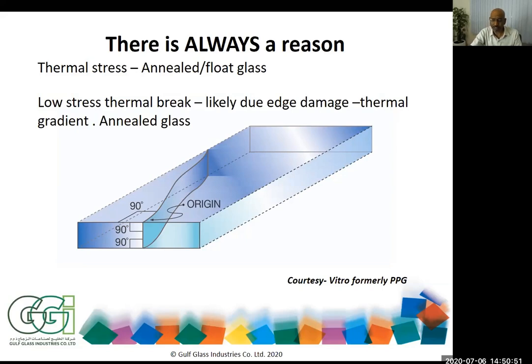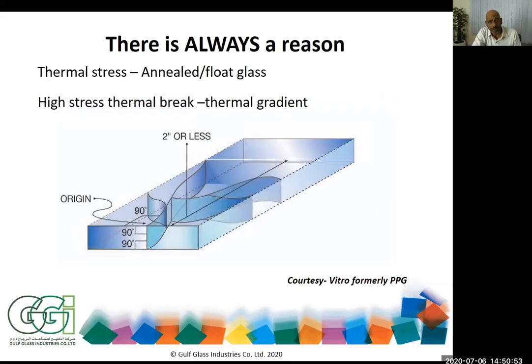But having said that, this is the high stress thermal break. And this can happen due to only thermal variation, thermal gradients. Many times, what happens to the glass is the edge of the glass, which is in the heavy framing, cools and remains cool, and the center of the glass is heated up because of the sun's exposure. And there's a temperature difference.